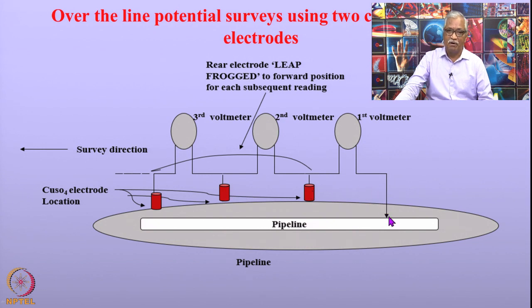First, you measure the potential of the pipeline with respect to the reference electrode by establishing an electrical connection here. Subsequently, the electrical connection is disconnected. Now, between the two electrodes, you measure the potentials. Then you leapfrog this reference electrode to the front and again measure the potential between the two electrodes. The algebraic sum of these potentials gives you the potential of the pipeline at a given location. The advantage of this technique is that the cable is very short, so one does not have to worry about the resistance offered by the cables.